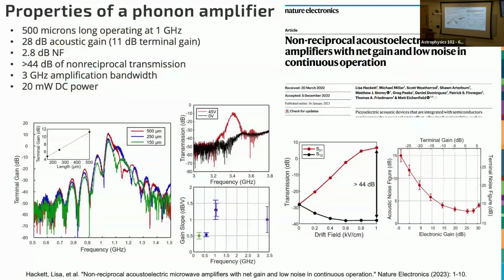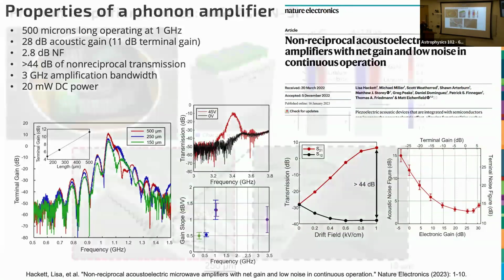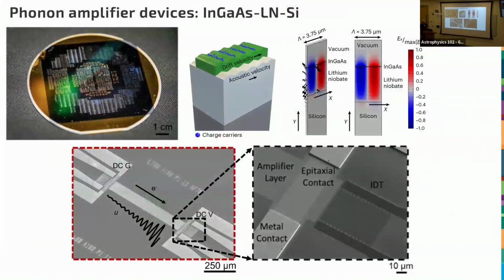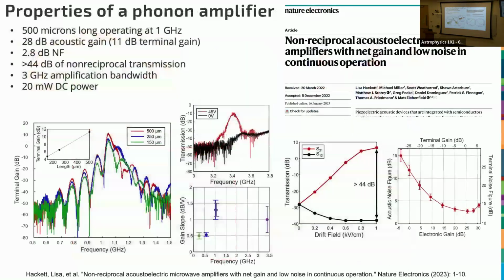So how well does it work? Well, it took us a while to get here. But as of last year, this was how well they were working. In about a 500 micron distance with a phonon frequency of 1 gigahertz, we can get about 28 dB of acoustic gain. So the acoustic power entering the device on the left, which we can calibrate, is about 1,000 times smaller than the acoustic power we get out. 28 dB, so pretty close to 30 dB.